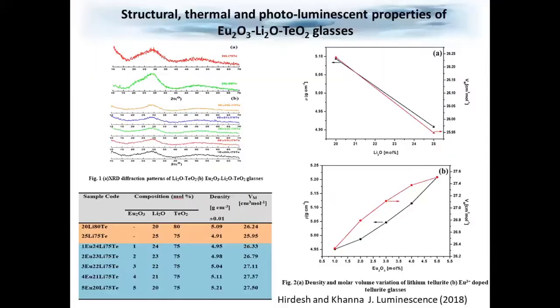So similarly, we have prepared europium doped lithium tellurite glasses. Lithium tellurite glasses have been reported to show fluorescence even in the absence of the rare earth ions. And you can prepare these glasses very easily at low melting temperatures of about 650 or 700 degrees Celsius. You can see the XRD patterns on the left-hand side, broad bands, because the samples are amorphous.